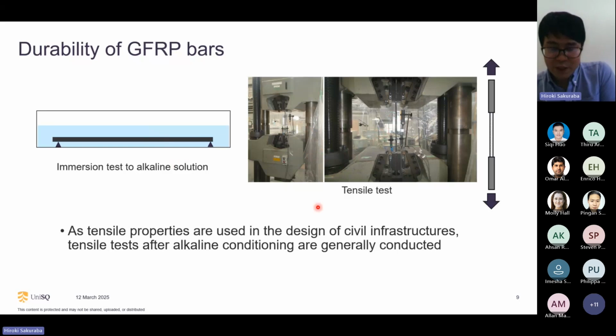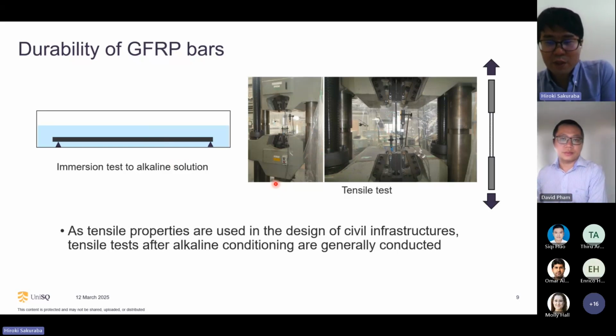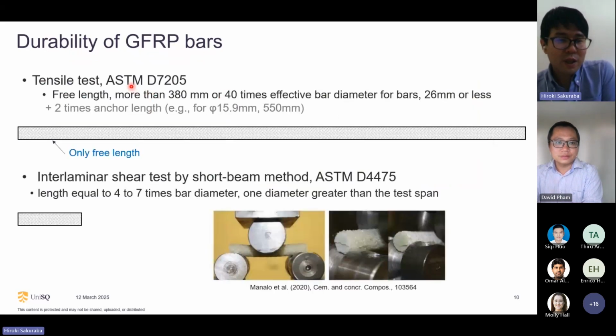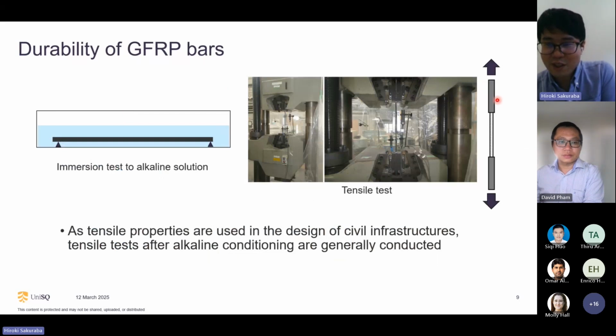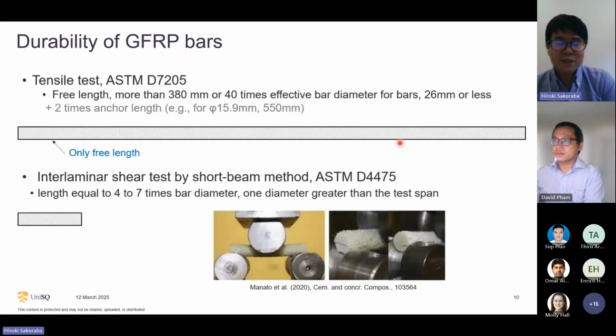But for studying field durability, this is really difficult because we need a long specimen. For example, based on the ASTM standard, only the free length we need is more than 380 millimeters. And also we need 2 times the anchor length. Anchor length means this length. So normally we need more than a 1 meter sample. So it is very difficult to take that kind of specimen from actual concrete bridges because it will damage actual concrete structures and it will stop traffic.